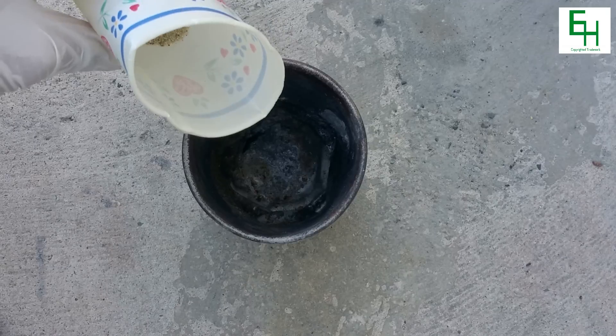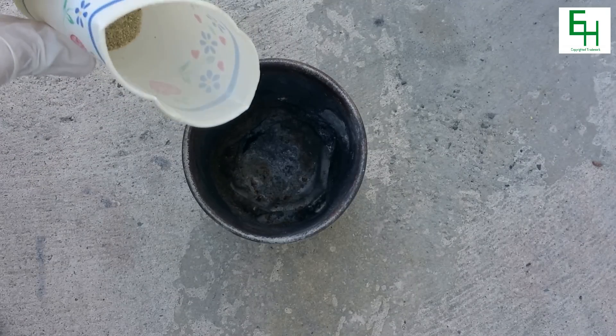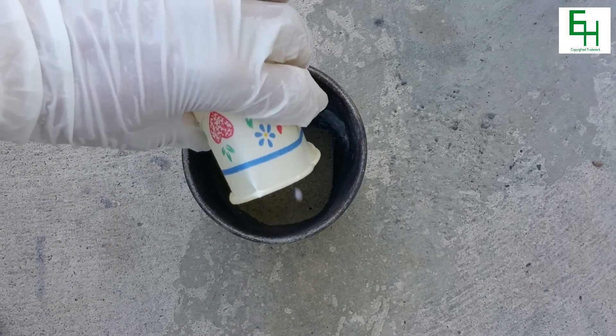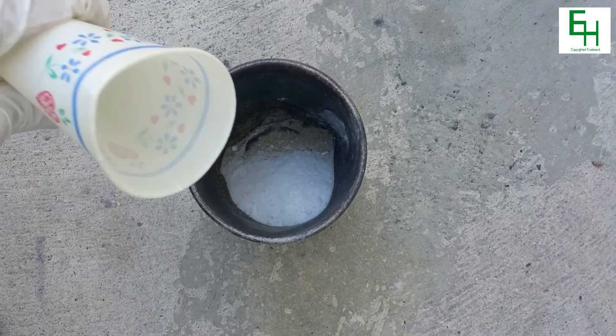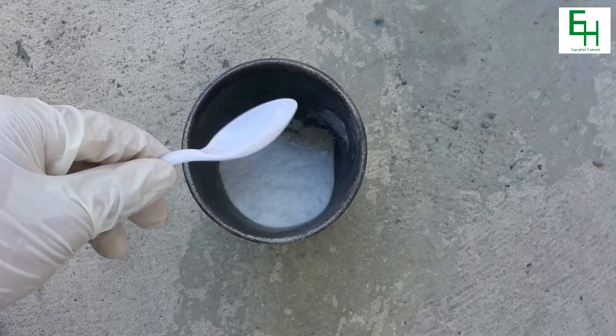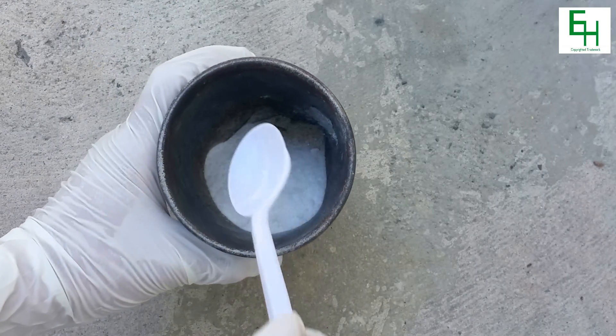I'm going to add in 32.5 grams of beach sand in an iron crucible. To that I'm going to be adding 10 grams of borax and 7.5 grams of baking soda. I'm also going to add a spoonful of table salt as flux, and this is going to make everything more smooth and runny. Now I'm going to mix all of it together.